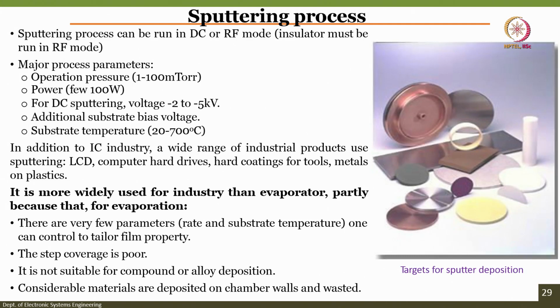For example, LCDs (liquid crystal displays), computer hard drives, and hard coatings for tools, metals and plastics all use sputtered films. It is more widely used in industry than evaporation, partially because for evaporation there are very few parameters, rate and substrate temperature, that one can control to tailor film properties. Sputtering has the advantage that we can tailor the film properties, as we have seen in the previous slide. The step coverage is poor for thermal evaporation, it is better for sputtering. Thermal evaporation is not suitable for compounds or alloys, while sputtering is.